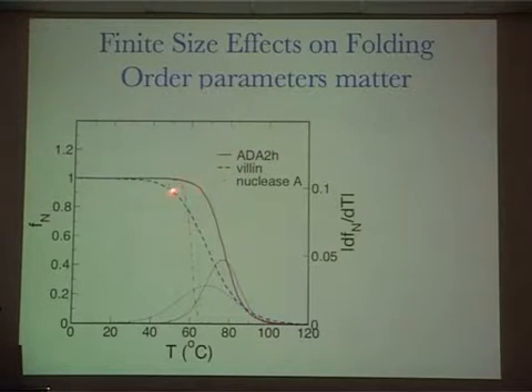If I look at this dash curve, you can just by eyeball tell that this is the least cooperative in some sense. It is not as sharp a transition as, for example, this dot dash and this green guy, which is very cooperative. It goes like that, right? Okay. The other curves are all derivatives of this curve to get an indication of the full width at maximum. So for the villin headpiece, the width of the transition is quite large. It's smaller for this protein. I think it's a 4-helix bundle, and this is ribonuclease A. So this is the kind of data that you would get.